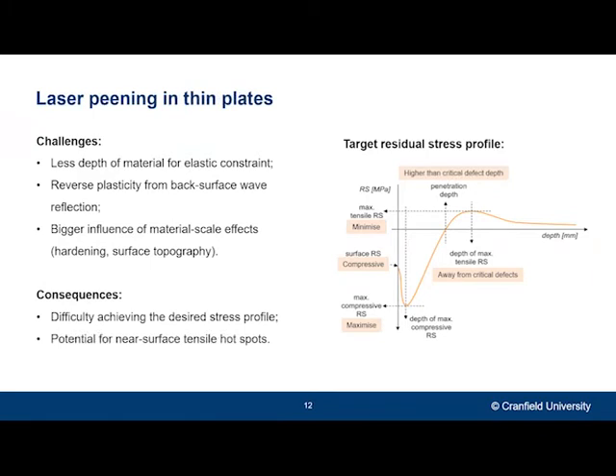However, peening over thin plates or sheet material, as we call it, is not straightforward at all. The reduced thickness of the plate involves many challenges to the process, such as back surface wave reflection and the fact that there's less material available for the elastic constraint. This makes it very challenging to achieve the desired residual stress fields that we are looking for in this